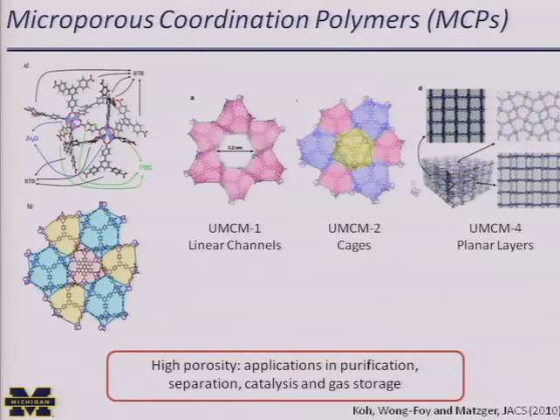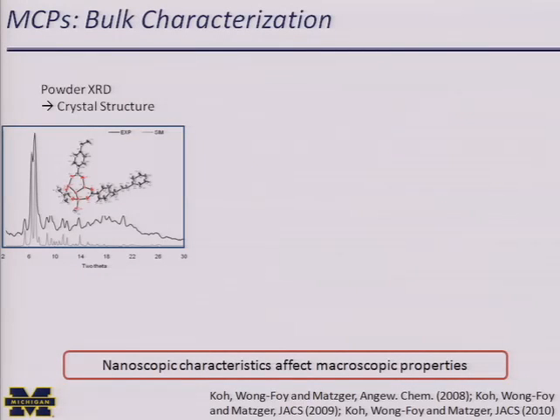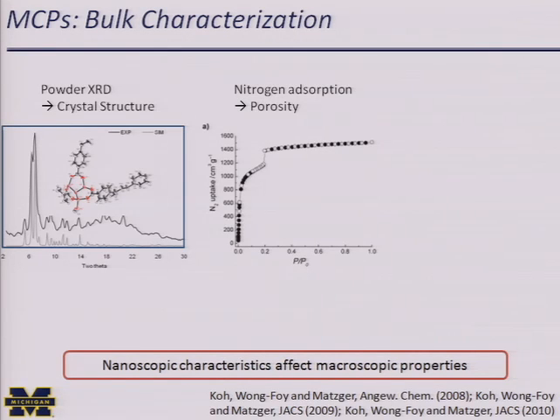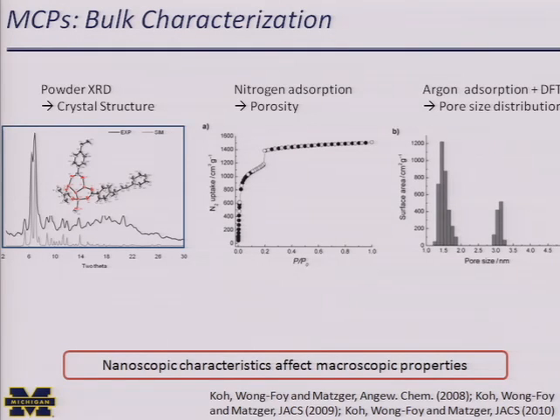So in general, there's many applications. And what we're interested in seeing is what does a guest molecule do when in these materials? And in particular, do the bulk characteristics really dictate the behavior? So the way that these materials are characterized in the bulk is by X-ray diffraction to get the crystal structure, by nitrogen adsorption to get the percentage porosity, and by argon adsorption plus some modeling to get pore size distribution. But clearly, it seems intuitive that the crystal structure is not everything.